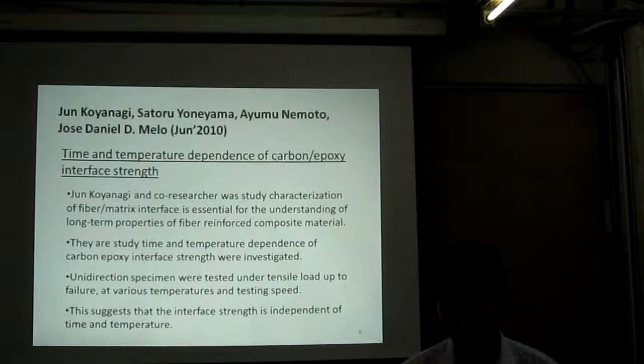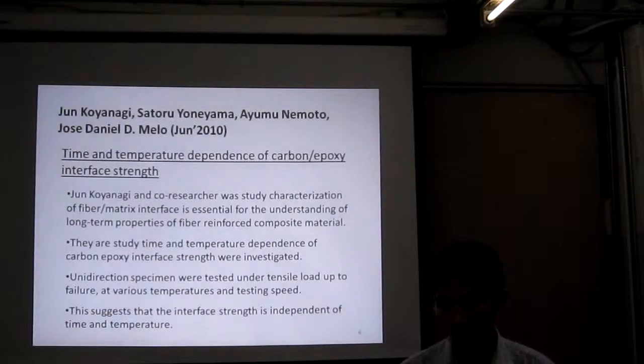In the time and temperature dependence of carbon epoxy interface strength, this research studied characterization of the fiber matrix interface for understanding of long-term properties of fiber reinforced composite. Time and temperature dependence of carbon epoxy interface strength were investigated, and unidirectional specimens were tested under tensile load up to failure at various temperature and testing speed, and found that in the testing condition the interface strength is independent of time and temperature.